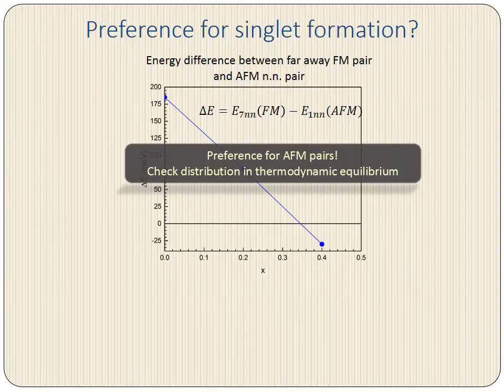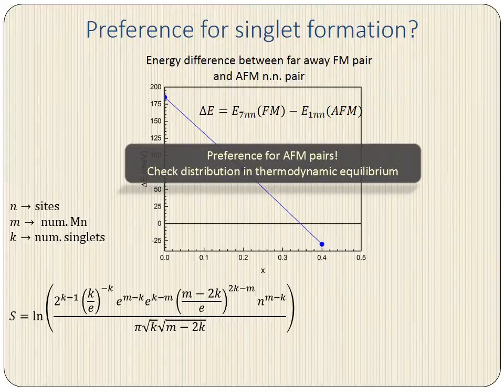So we need to return to our combinatorics problem again. We again start with that square lattice, we set the number of manganese atoms that are total in our system, and then we portion off a certain subset of those atoms to be in singlets. We work out the total combinatorics, take the natural log, and then we obtain the entropy in the dilute limit. Note that in this expression, n is the number of lattice sites, m is the total number of manganese atoms, and k is the number of manganese singlets.